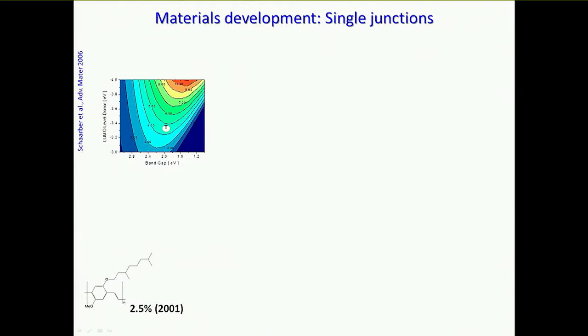And what followed, going really from the very beginning of the first 2% efficient bulk heterojunction solar cell, was that efficiencies improved because of new materials. And we can track what happened: first of all, a material that absorbed a bit too far in the blue was replaced by polythiophene, which is absorbing in the green, so it's better, it has higher mobility.